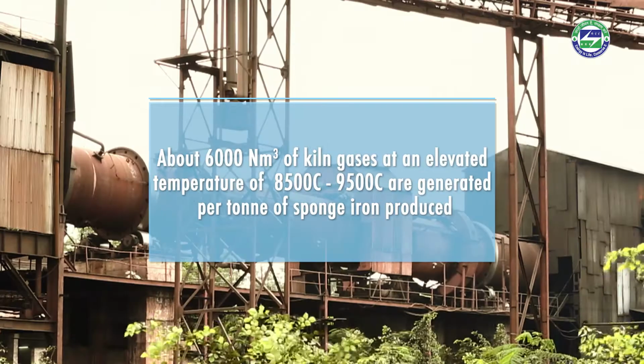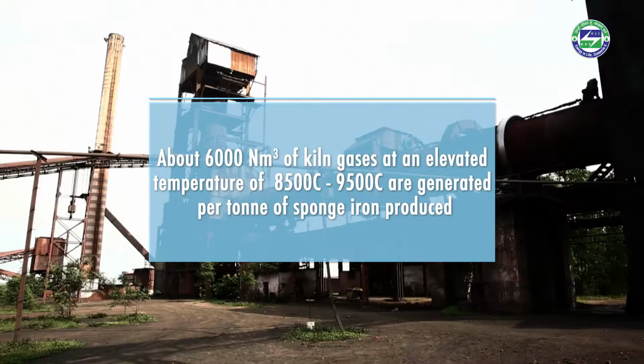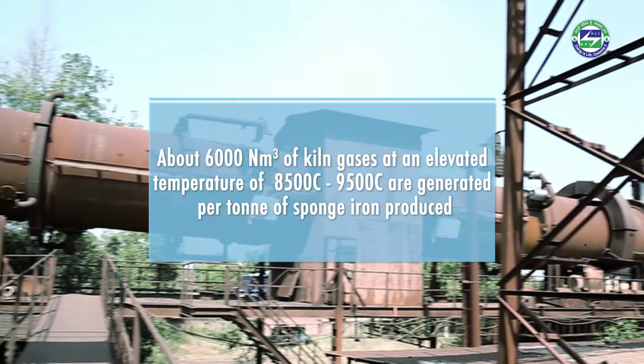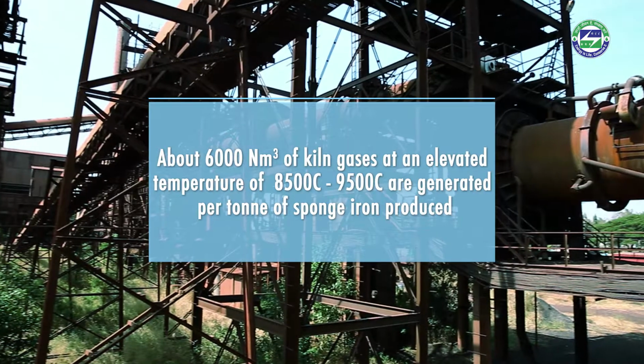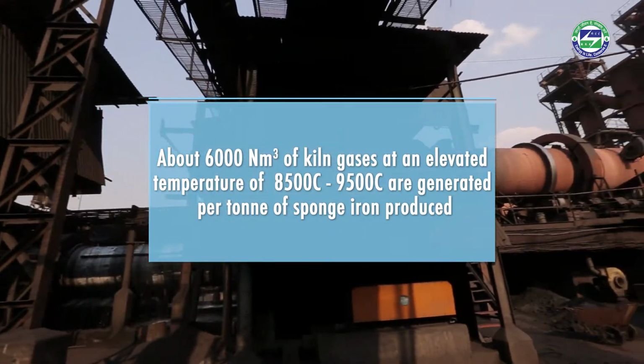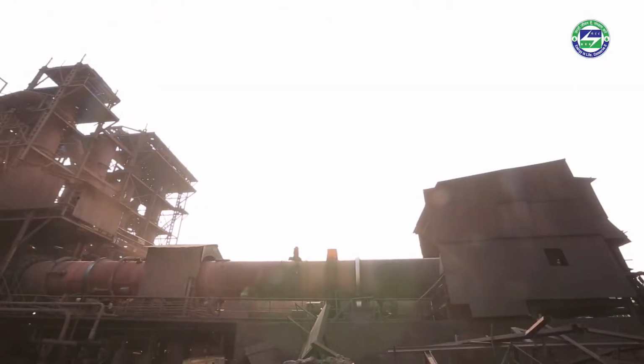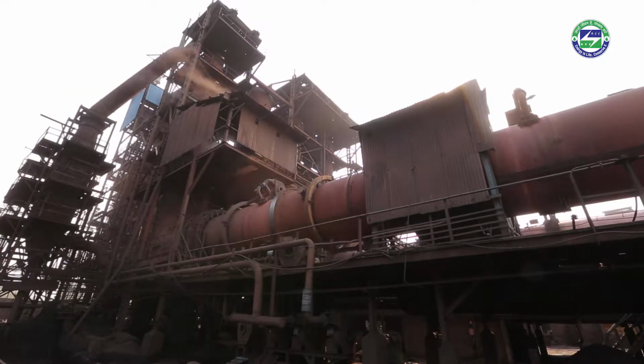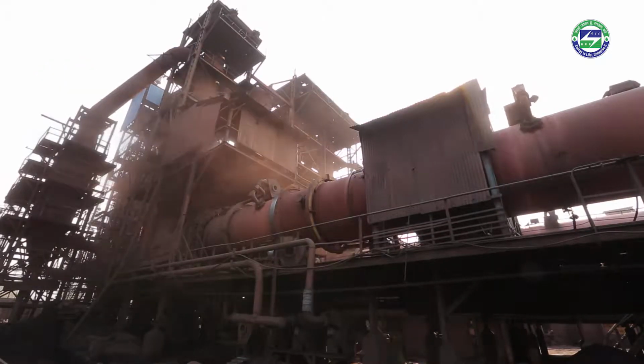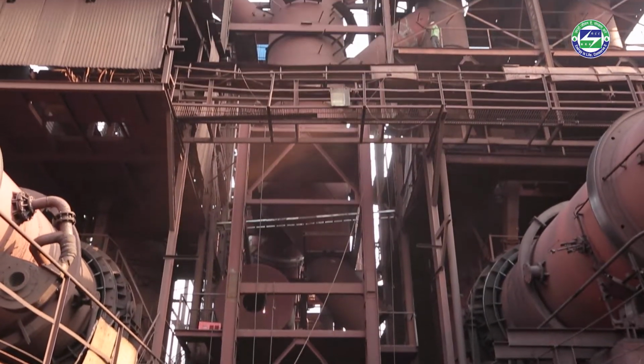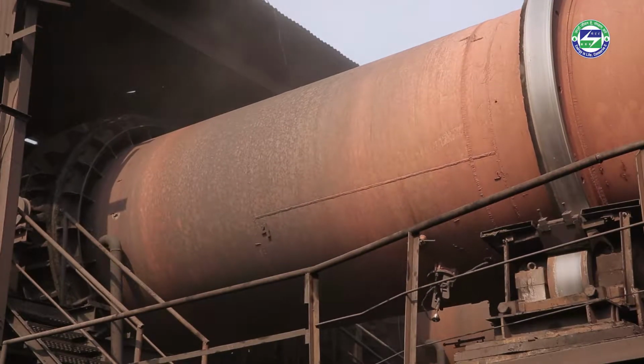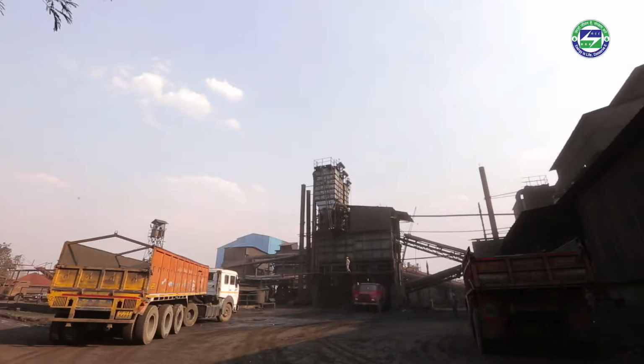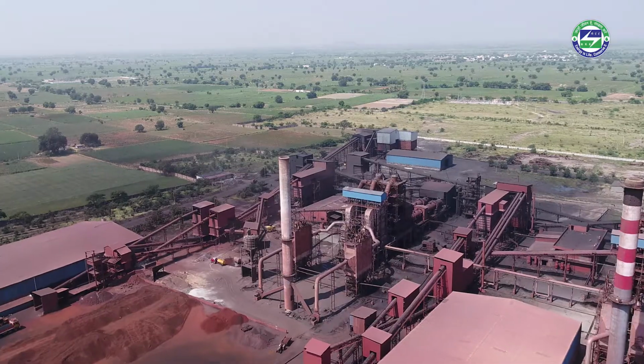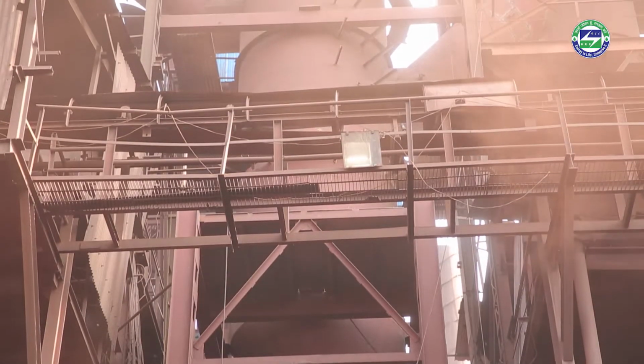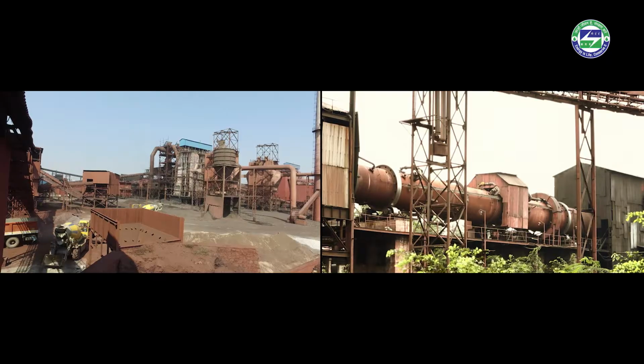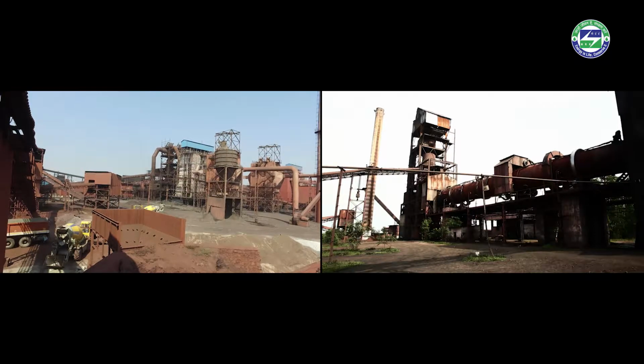About 6,000 normal cubic meters of kiln gases at an elevated temperature of 850 to 950 degrees Celsius are generated per ton of sponge iron produced. Under conventional practice, these gases are cooled down to below 200 degrees Celsius with the help of a forced draft cooler and later passed through an electrostatic precipitator for complete elimination of dust particles before letting it out through the chimney. In the process, not only is a considerable amount of sensible heat wasted, but extra energy is also used for the cooling of gases.